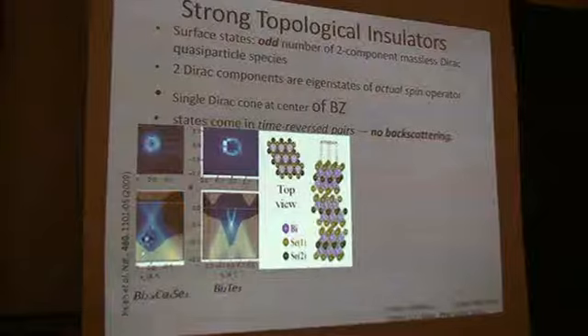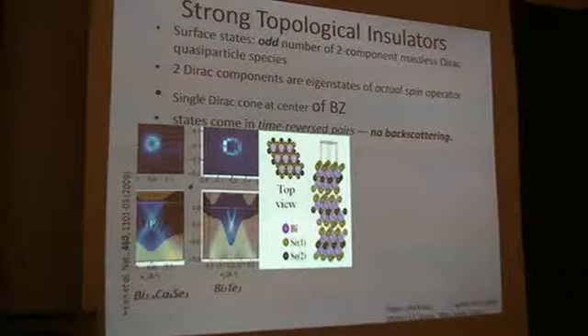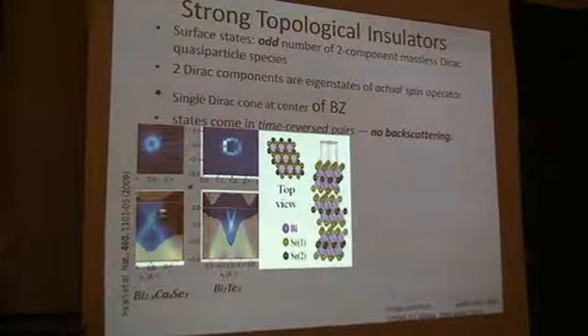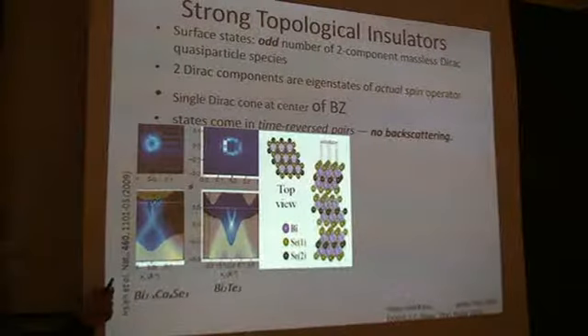Okay, so this Dirac cone with the assignment of the spins was beautifully demonstrated by a number of ARPES experiments by Princeton and Stanford groups, and that's the material we're talking about, bismuth selenide, Bi2Se3. Here is the Dirac cone for the calcium-doped one, where they hope to put the chemical potential close to the crossing point.